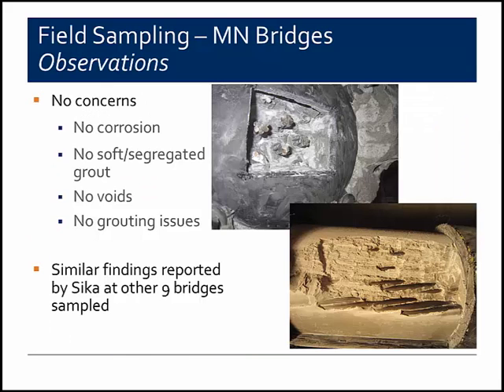And so through the sampling process on all three bridges, what we found was essentially no concerns. There was no corrosion at any location, no soft or segregated grout at any location, no voids, and no grouting issues. Everything looked good. And although we were not involved with the other 9 bridges that were targeted for field sampling, the same conditions have been reported at those bridges to the best of my understanding.